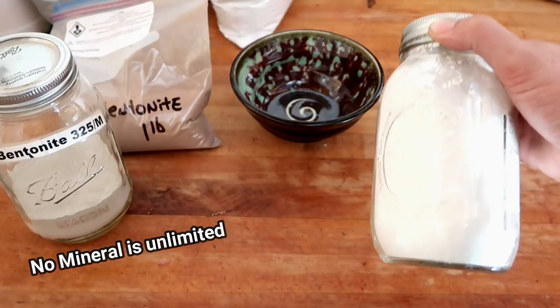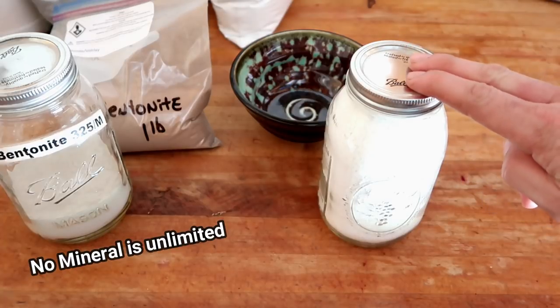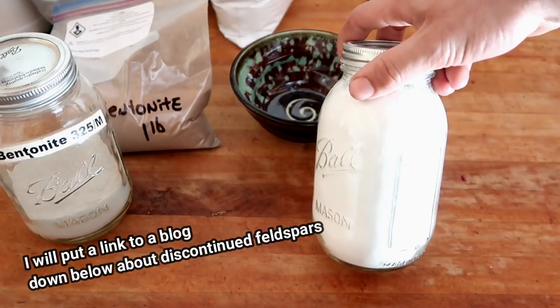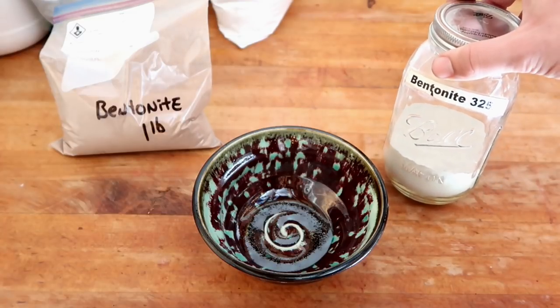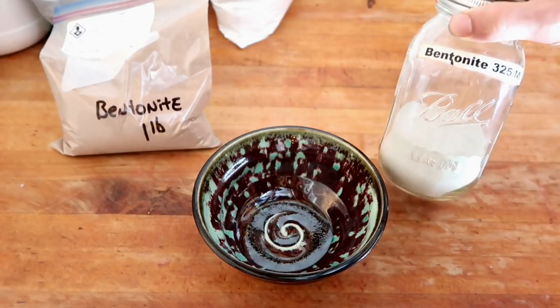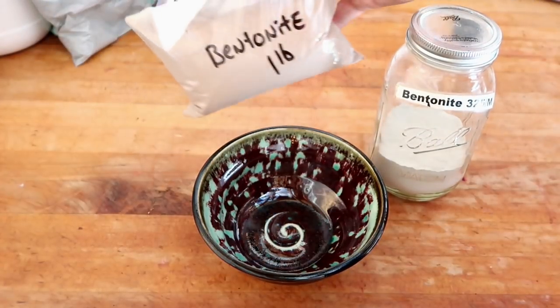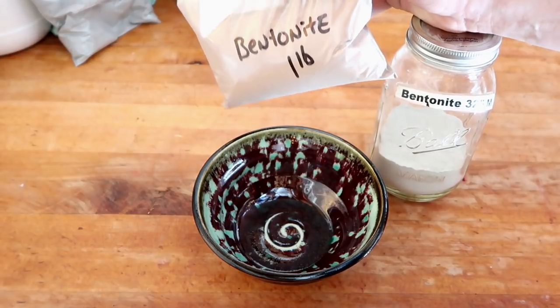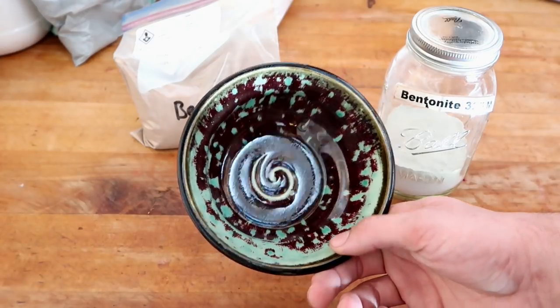We don't have F4 Kona Feldspar anymore. So if you go to most ceramic stores and ask for it, they will most likely just give you Custer Feldspar instead, because the actual F4 Kona Feldspar — the pure stuff — is no longer available. When I was testing this glaze, I tested it with this bentonite right here, and it seems I can't get this bentonite anymore. The company changed pits. Even though it is technically the same chemical and made up of the same elemental properties, there are still most likely small, minor changes — and even the smallest changes can have adverse effects on your ceramic artwork.